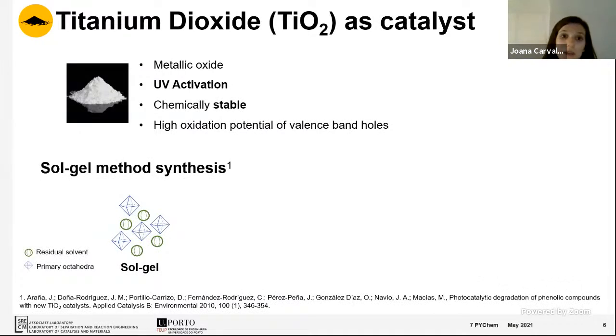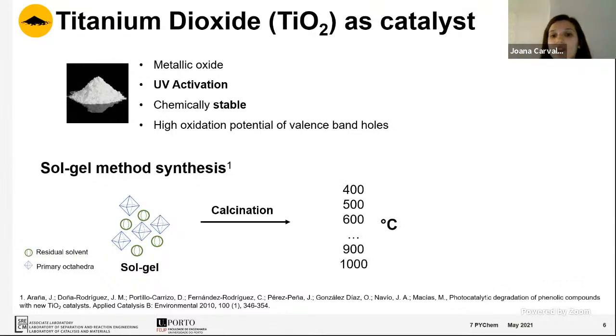It's a simple and easy method that normally involves the synthesis of a precursor that undergoes calcination in order to form the crystalline phase. In this work, I used different calcination temperatures, between 400 degrees and 1000 degrees. I started at 400 degrees because it is the temperature necessary to overcome the amorphous phase of the material.